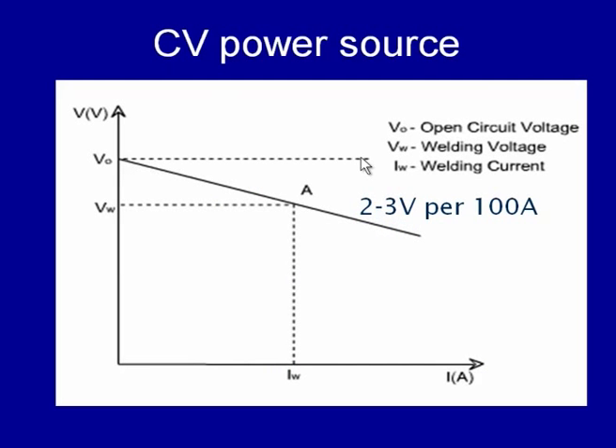And this is what we can see: theoretically, the constant voltage power source should offer the characteristic of this kind, but actually it does not offer this kind of relationship. Here, with the increase of the welding current, there is a marginal decrease in the arc voltage, and this decrease is about 2 to 3 volts per 100 ampere current.